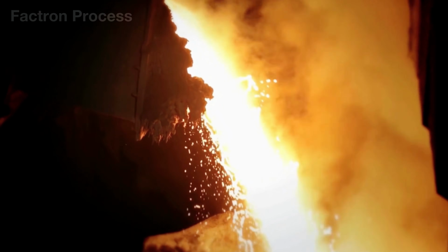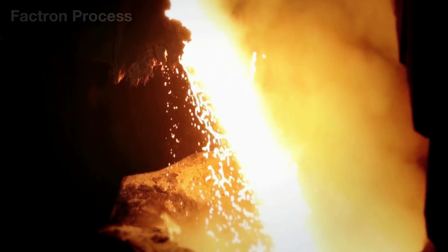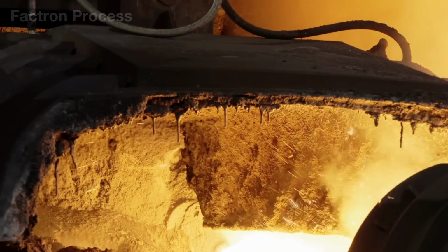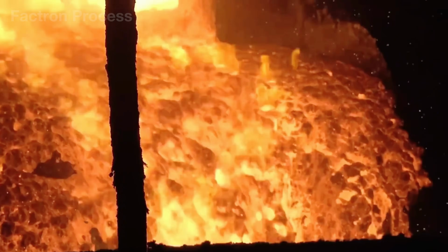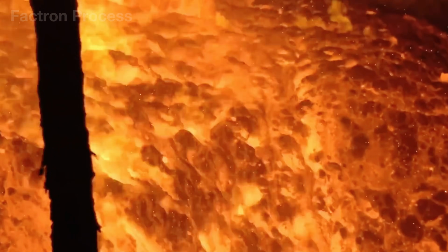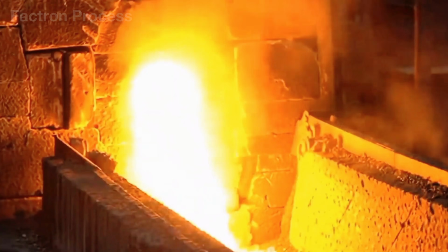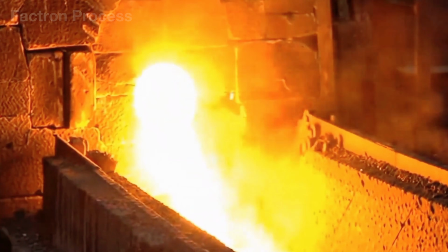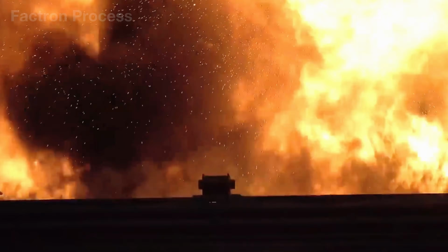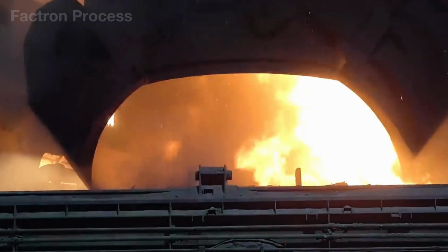Inside the furnace, the added quicklime and dolomite react with oxidized impurities, binding them together to form a thick layer of foamy slag floating on the surface of the molten steel. This slag acts as a protective shield, preventing the liquid metal from absorbing nitrogen and hydrogen from the air, while also retaining heat and removing non-metallic impurities.